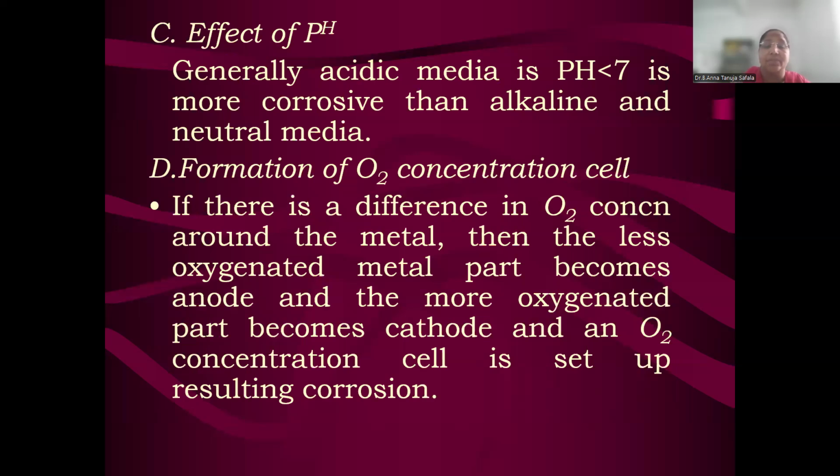Then if we come to oxygen concentration, if there is a difference in oxygen concentrations, that leads to anodic and cathodic regions, and there will be a high rate of corrosion at the anodic part. You all know that the highly aerated part will become the cathode, and the less aerated part will become the anode.